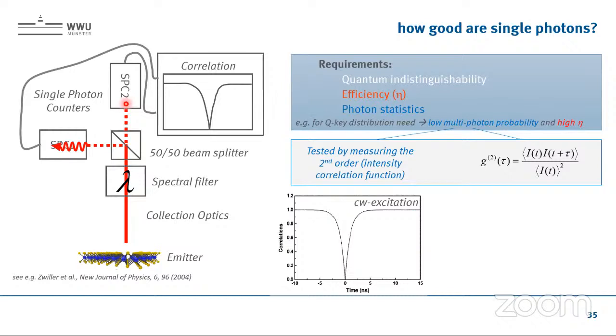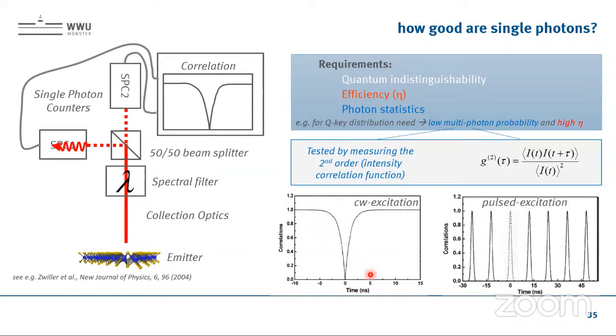And that's exactly in a continuous wave experiment where we have a different delay time. We have ideally 0. Due to the background and some uncertainty, we typically say we have a single photon event below 0.5. Or in pulse excitation, it would mean, depending on the pulse duration or the frequency of the pulse, we would also have this kind of peaks, and the zero peak would be missing.